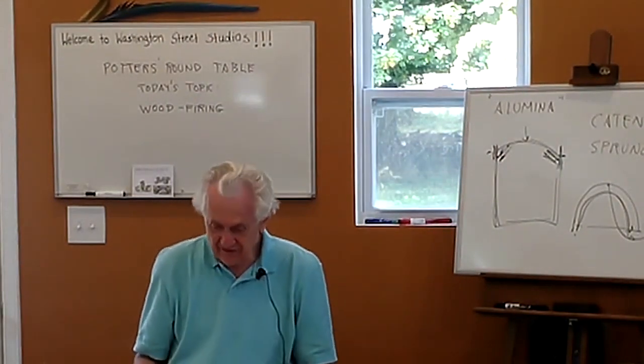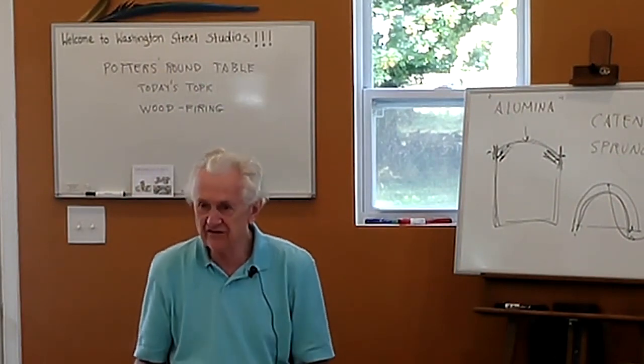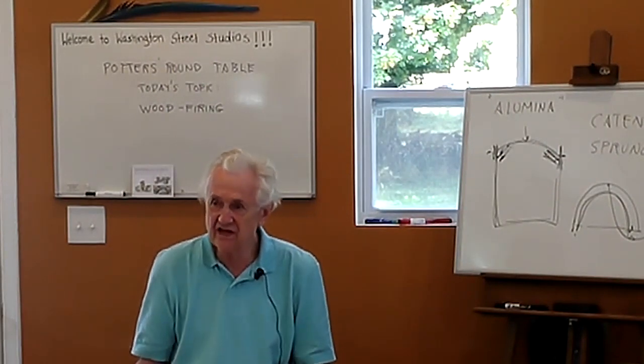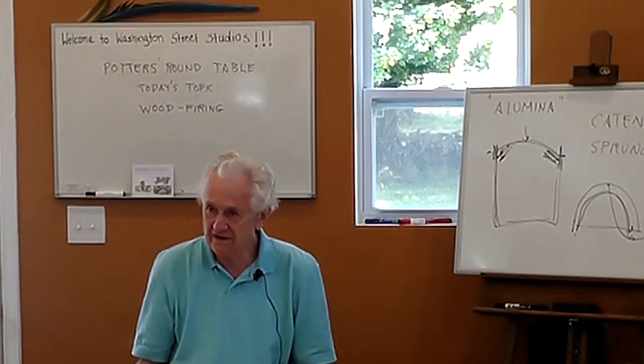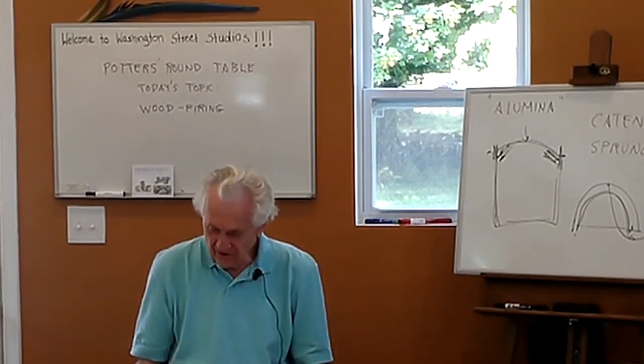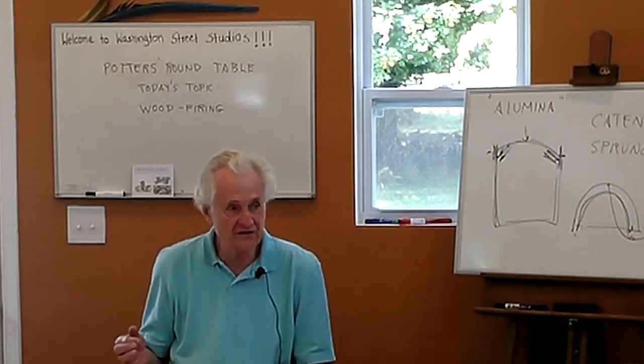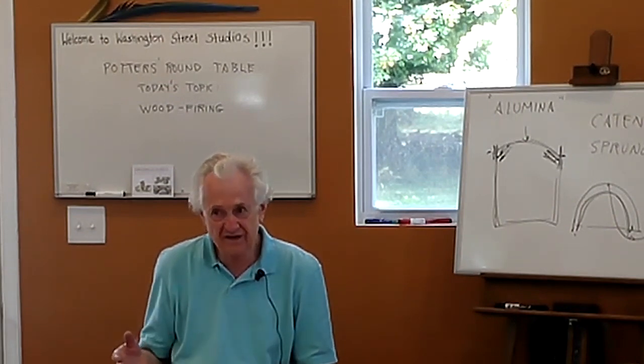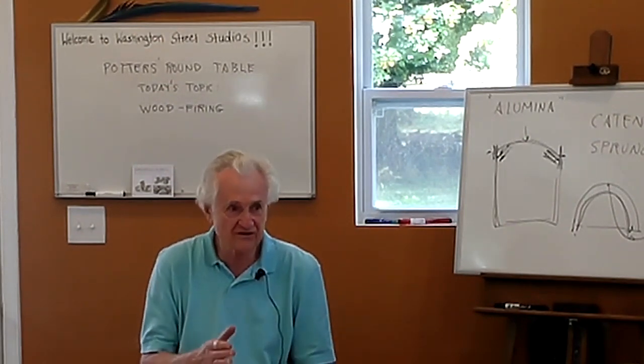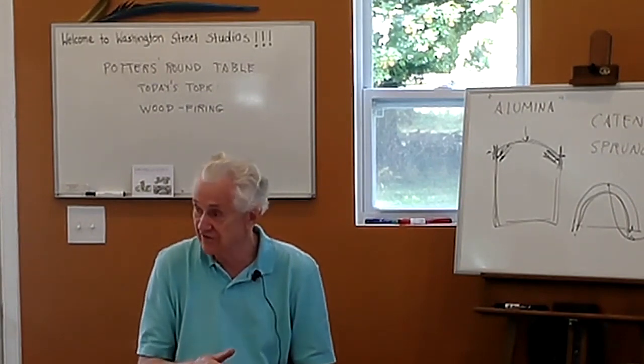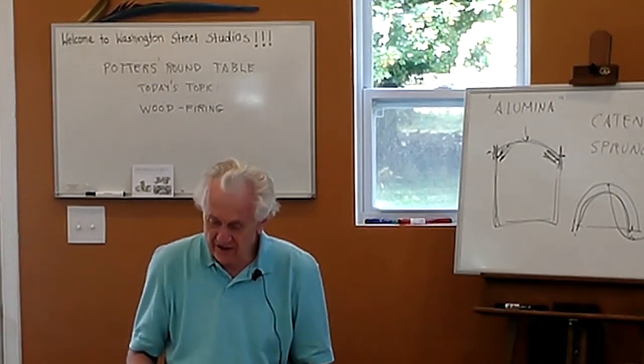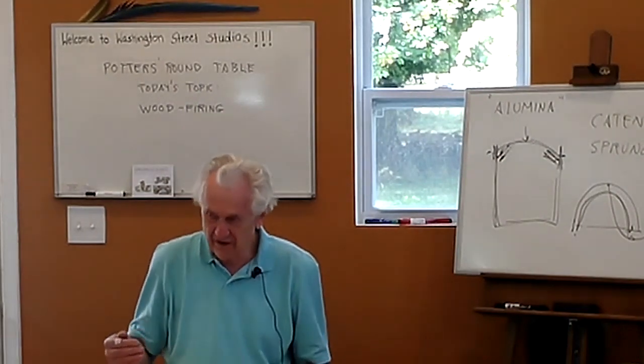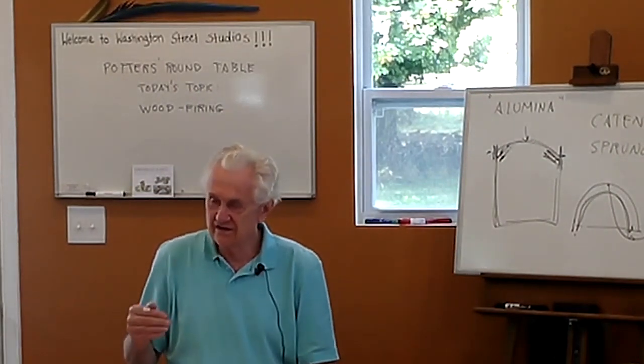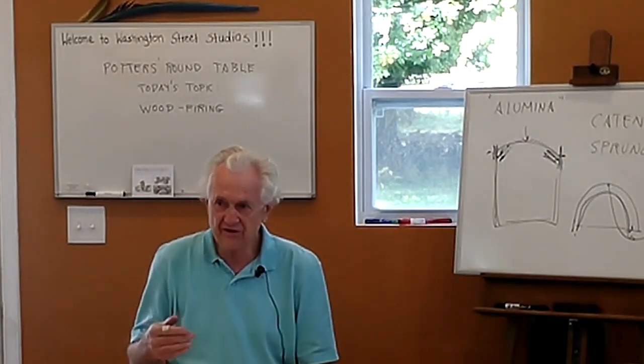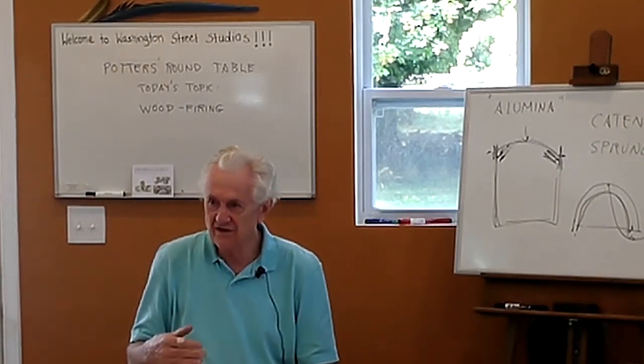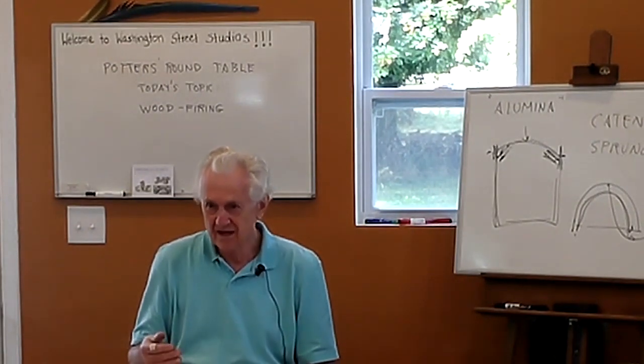The other thing is construction details. If you're thinking about building a kiln, you need a shelter over the kiln to protect it from the weather. And you also need a shelter if you're going to have firewood: some place to store your wood so that it stays dry. One of the reasons you need the shelter over the kiln, among other things, is that if the kiln is exposed to the weather for a long period of time, the bricks will absorb water, and then you can blow up your bricks when you heat up the kiln.